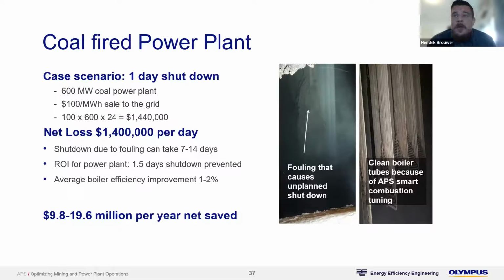So we can avoid one of these shutdowns by making sure that the ash stays in a solid form and does not melt and become slag. In the first picture, I would like you to have a close look where the arrow is. These are pendant superheater tubes that are hanging inside of the furnace. Now, this buildup that you see here is approximately the size of a car.